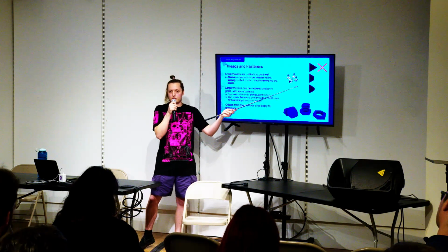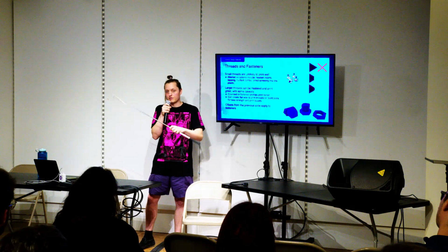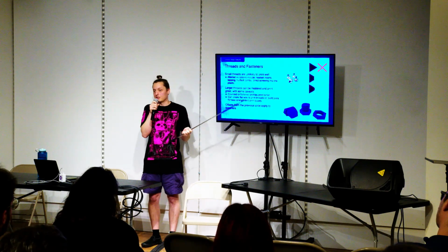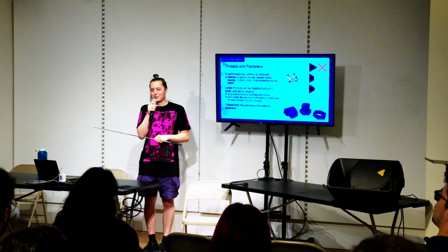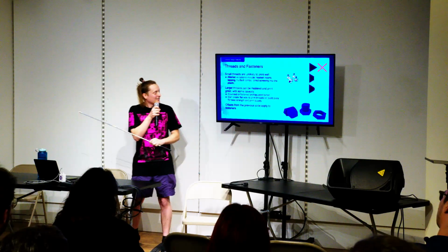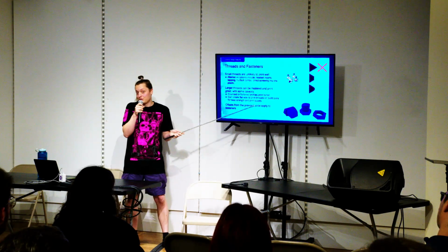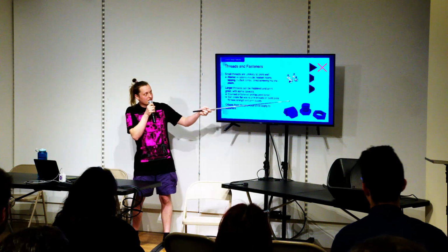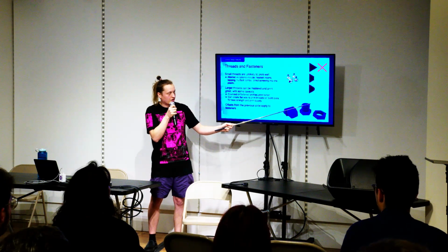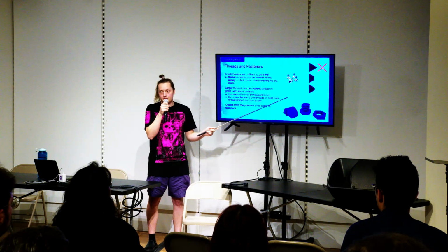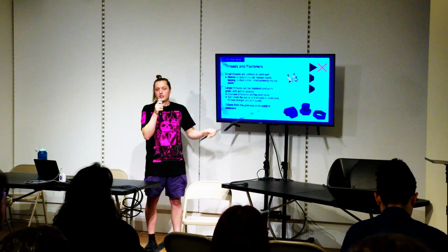You just use a soldering iron to heat them up and melt them into a hole in the surface of your plastic. And they generally are stronger than any other option. Usually your part will break before they get pulled out of the print. So then for larger threads, you can model them and they do print great. A couple caveats are you don't want a really sharp profile to the edge of your thread. It's generally best to just cut it flat or round it off to get a better print result.